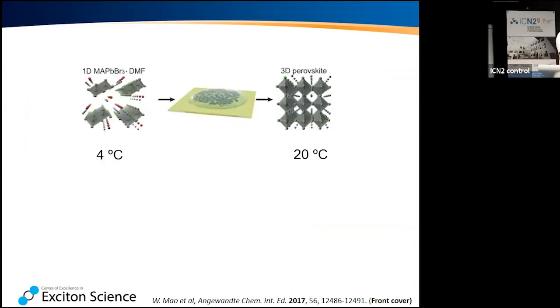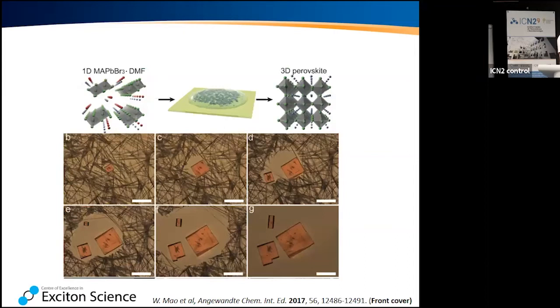Now, the nice thing is if you take them and you put them on a surface, a droplet, and you let it warm up to room temperature, the perovskite is going to form. And now, because we had to shift my talk from my laptop to another computer, the next video is most likely not working, but that's why I have my backup here. So here you can see that at the very beginning, you have mostly your 1D material. And as it warms up, you can see how the needles start to melt and go away. And then your perovskite platelets start growing.